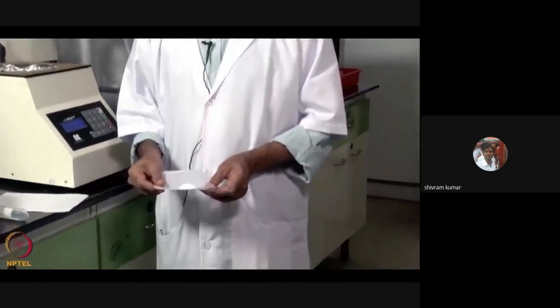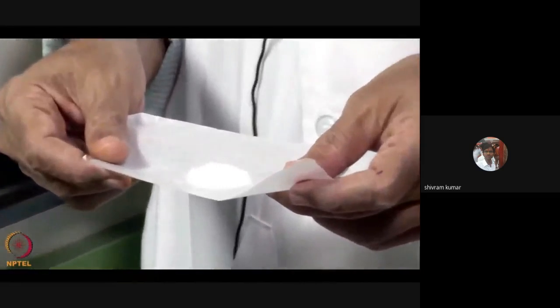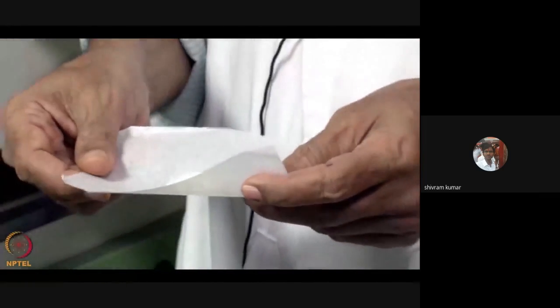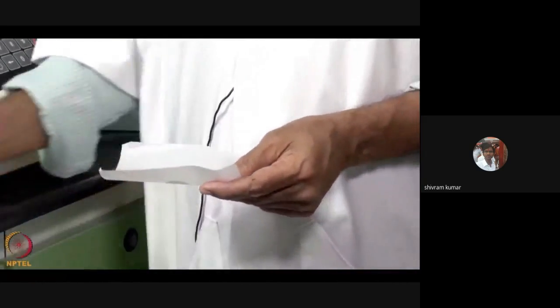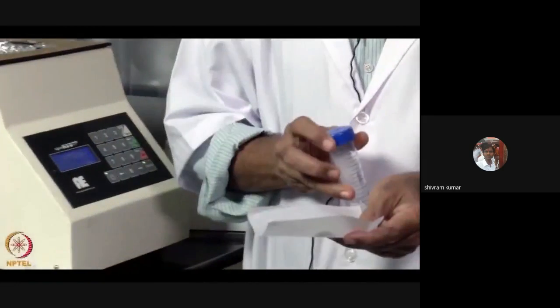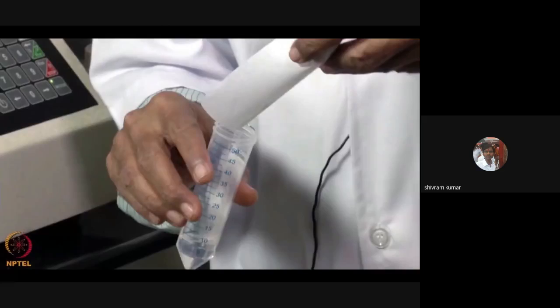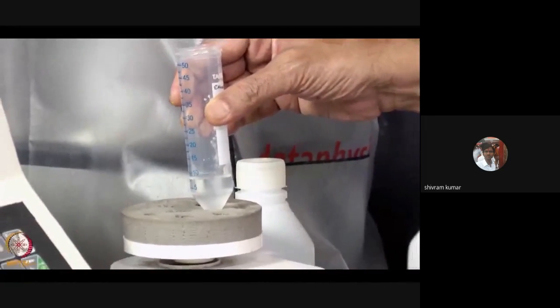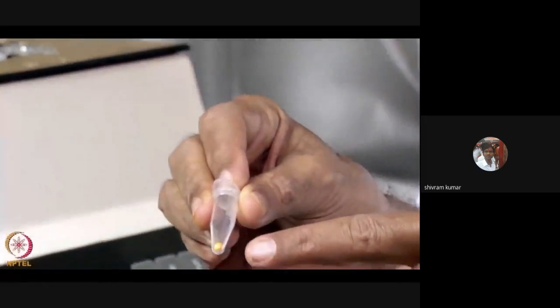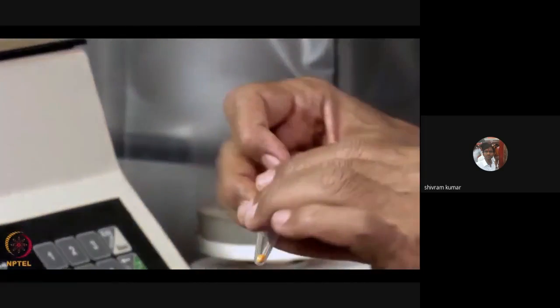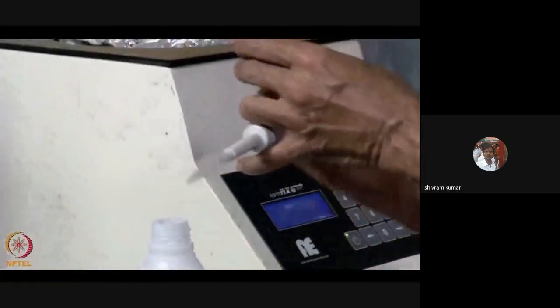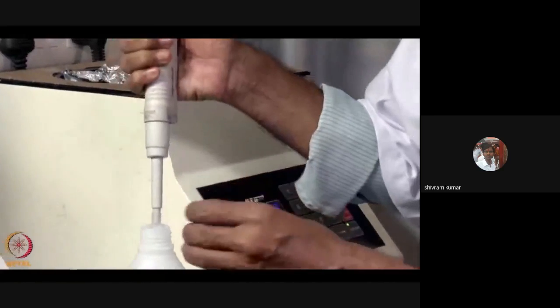I take this polyvinyl pyrrolidone, that is PVP, 1 gram of it, okay, with a molecular weight of 40,000, in 10 ml ethanol. And then we mix it thoroughly, okay, for about 5 minutes. We use a vortex mixer for mixing this thoroughly. We take 5 milligrams of curcumin and we add 1 ml of ethanol to it. As you know, curcumin is not soluble in water.